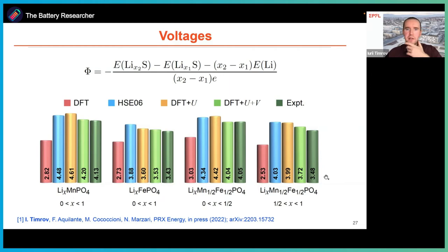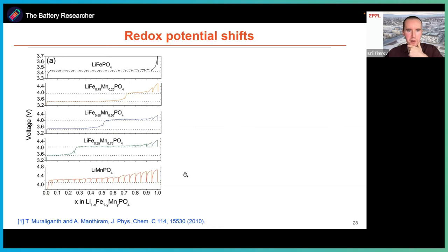Another interesting point that I would like to discuss is the redox potential shifts. This is from the experimental paper shown below. Voltage profile at different concentrations of lithium and different compounds. So in the iron olivine, we have one plateau with the voltage of 3.43 volt. In manganese, there is also only one plateau. But in the intermediate case, when we have 50% of iron and 50% of manganese, we have two plateaus. The first plateau is similar to the voltage of the pristine iron olivine. And the second plateau is similar to the voltage of the pristine manganese olivine.